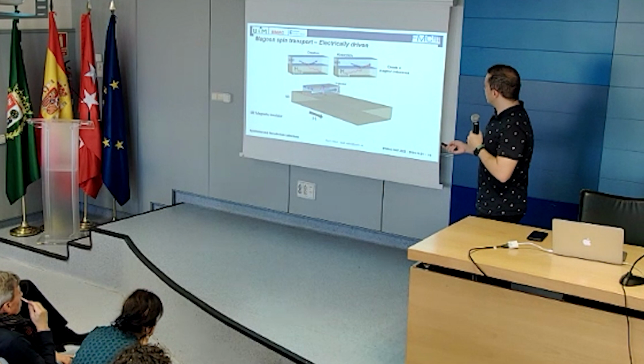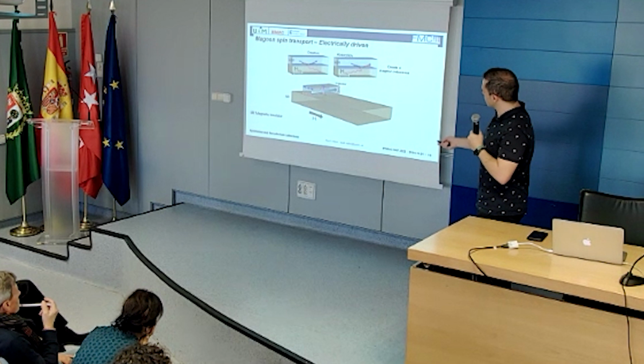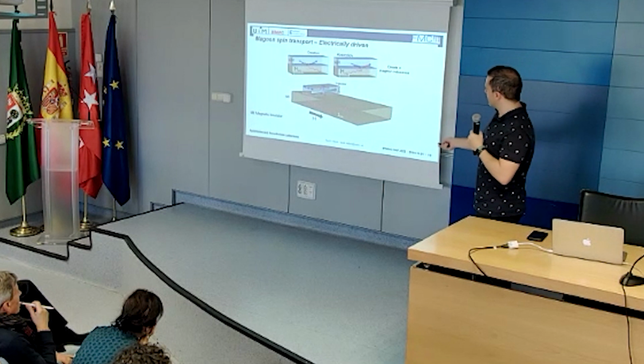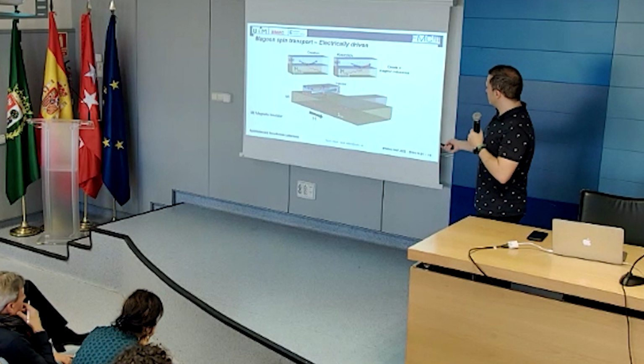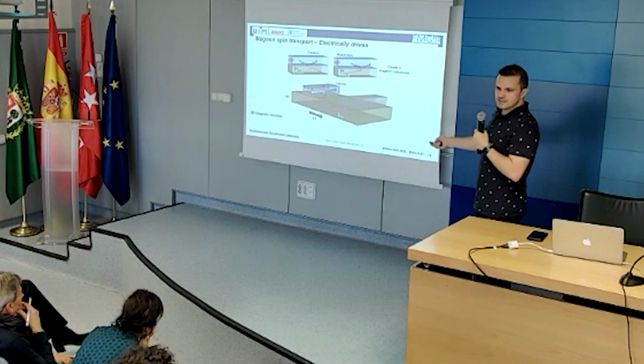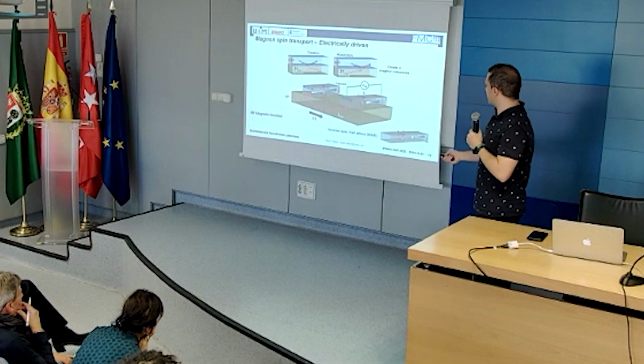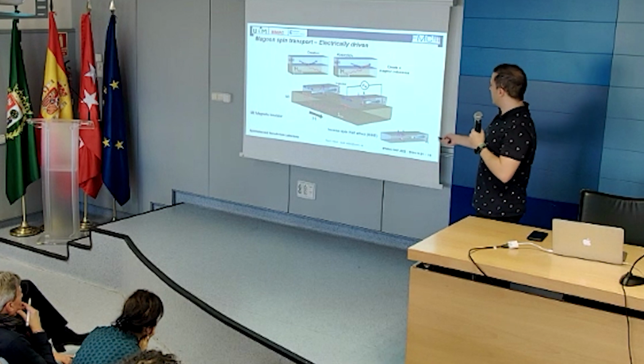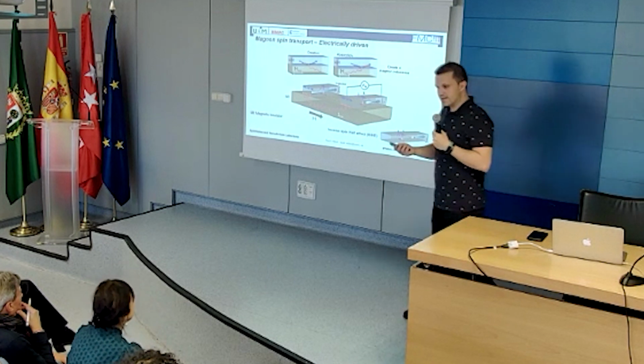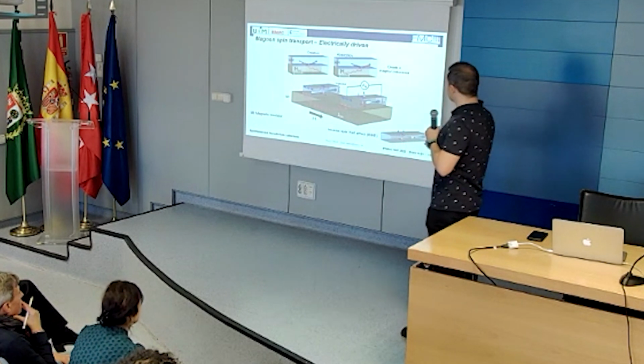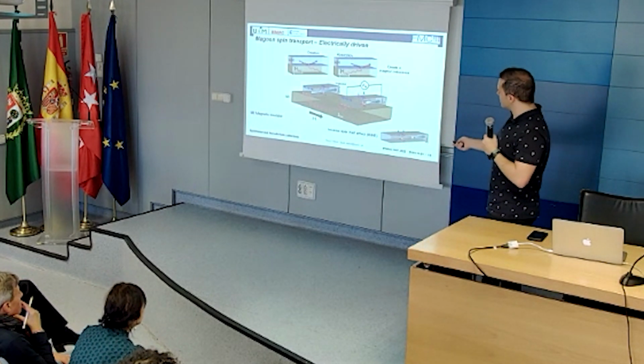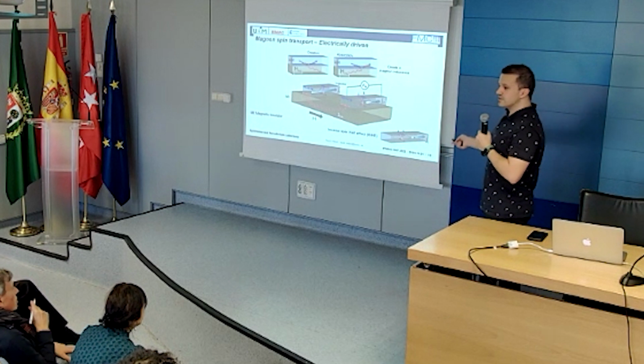But now, if you place this electrode on top of this magnetic insulator, now you run a current, and because of these magnons, they can also propagate, right? They are propagating because you have interaction here, so you can generate these magnons, and then you place another electrode, and even though this is not electrically conducting, you can transport spin information through this magnetic insulator. And then you can pick it up with a reciprocal process. Through Onsager reciprocity, you will get exactly the opposite process. You will convert these magnons to a spin current, and this spin current to a charge current. What you're picking up here is a voltage.